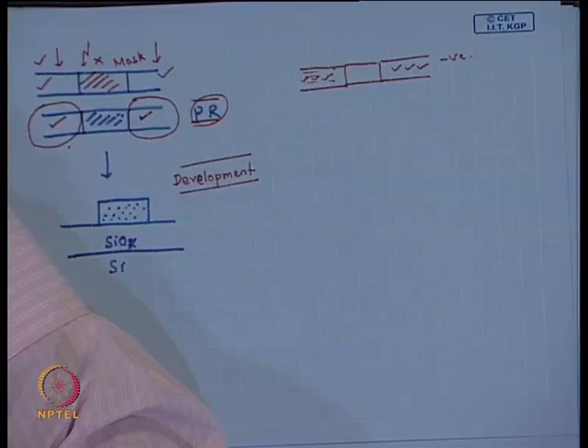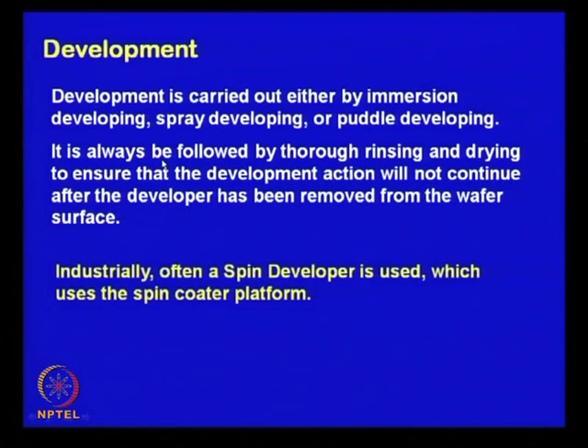Development is carried out either by immersion developing, spray developing, or puddle developing. It is always followed by thorough rinsing and drying to ensure the development action will not continue after the developer has been removed from the wafer surface. Right after development, the patterned wafer must be dried thoroughly, because remnant developer solution remaining on the structures will continue the dissolution process and damage the fidelity of the pattern.